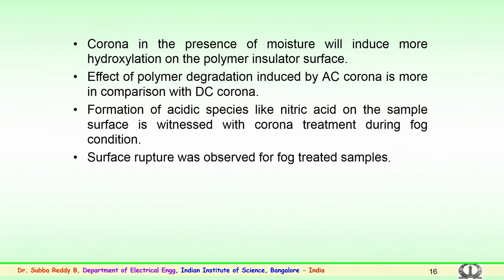We have seen that corona in the presence of moisture will induce more hydroxylation on the polymer insulator surface. Very important point. The effect of polymer degradation induced by the AC corona is higher in comparison to DC corona. So, experiments have been carried out for both AC and DC voltages, and the comparison has been made, and the degradation effect is seen to be higher when AC corona is applied on the sample in comparison to the DC corona. This is because of the surface charging; space charge which is formed on the surface could be one of the reasons for the lesser degradation in comparison to the AC corona.